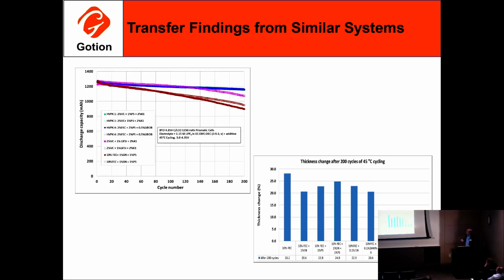What you can see is, standard electrolyte, about 80% capacity retention after 200 cycles. By putting in the right additive combinations, you can get up to about 95%. So a significant improvement just by the additives that help protect the cathode and also protect the anode. And then, of course, we want to maintain the low swelling. So again, this is the target, to get this up and keep this low. This is 45C cycling after 200 cycles, looking at the swelling.